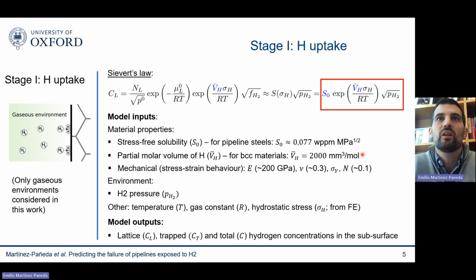There's no uncertainty here. And then, of course, because we need to calculate the hydrostatic stress, we need also a mechanical description. So we need a Young's modulus, which we know what is the value for steels, Poisson ratio, yield stress, which we're going to consider various different types of pipeline steels with different yield stress, and then the strain hardening exponent, which is typically around 0.1 for this kind of pipeline steels. And then we need information from the environment, the hydrogen pressure, again, something that we know very well. And then, of course, we need also temperature, gas constant, and hydrostatic stress that you get from finite elements. So there's really no fitting parameters or no uncertainty. We can quantitatively predict what is the hydrogen uptake in here.